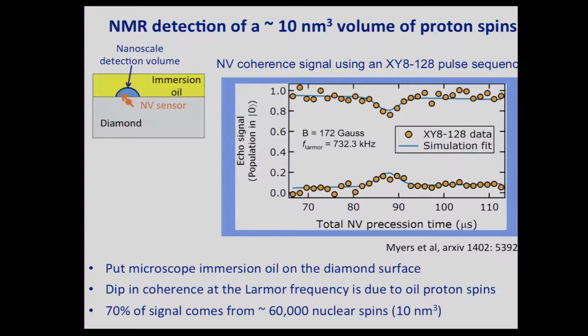The nice thing here is that oftentimes one quotes the sensitivity of the NV center, but you're talking about an NV center that's inside a bulk piece of diamond, which is very well protected from its environment. But here we've really brought our sensor right near the surface, and actually in the presence of fluctuating spins and whatever's on the surface. So this was a nice demonstration that it works. The total number of spins that we're detecting in this 10 nanometer cube volume is 60,000. Again, we're trying to get to the single nuclear spin limit, and we think there are pretty good prospects of getting there within the next year.